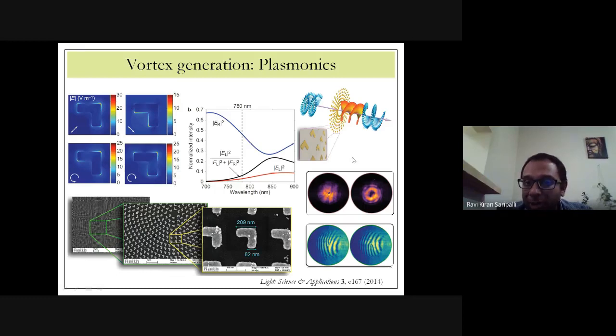And that is what they show when you come in with a left circularly polarized beam on this plasmon structure. The right circularly polarized converted component will generate an orbital angular momentum. And this is the plot of the conversion efficiency. They were able to very efficiently generate a spin orbit interaction in these kinds of materials. And the way to say whether it is an OAM beam, of course, you get these donut shaped beams, but when you interfere with a Gaussian beam, you start seeing these fork kinds of patterns. And by seeing the fork patterns, you can tell the charge of the vortex or the OAM beam.